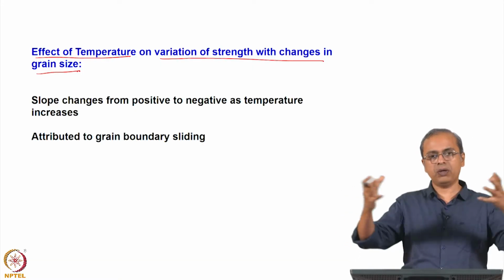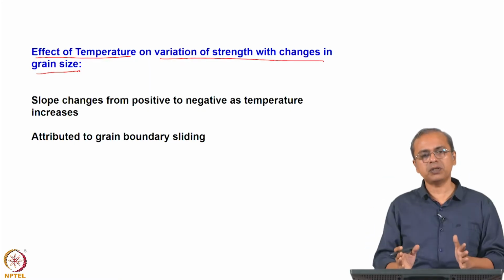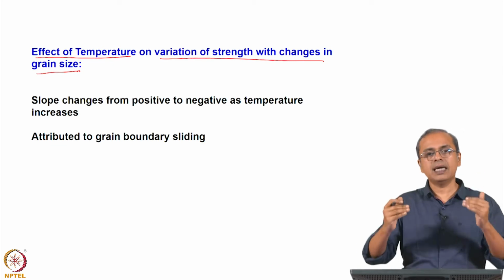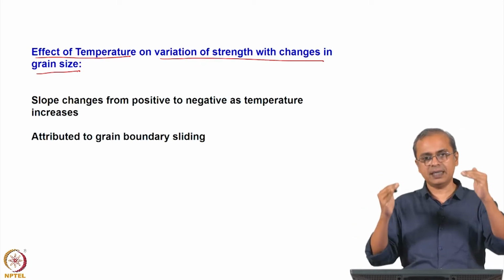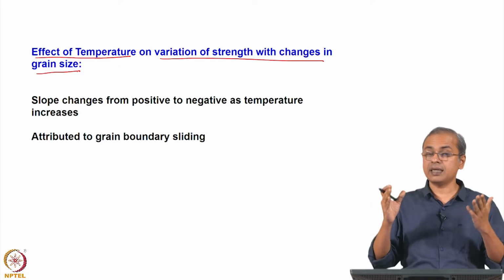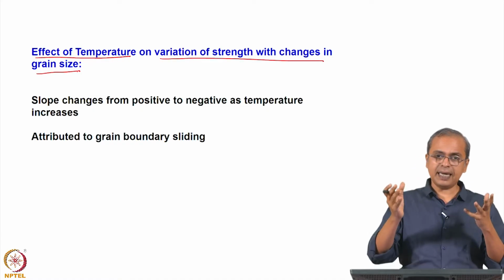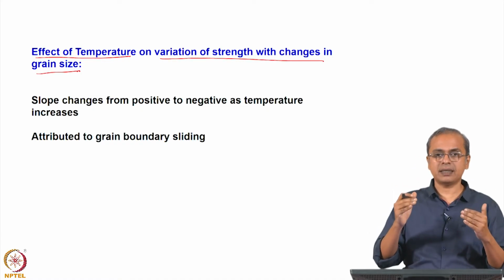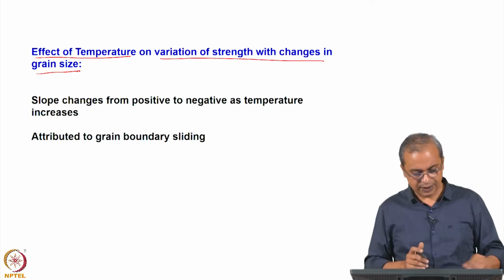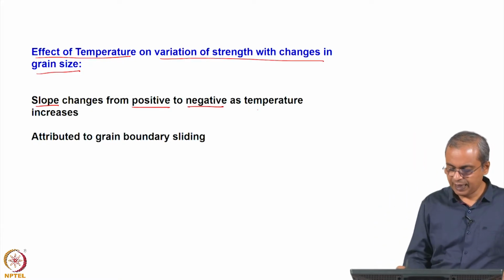So, effectively it is the Hall Petch relationship at one temperature. Then you look at the Hall Petch relationship for the same set of samples at a higher temperature, and you keep on raising the temperature. If you cross some temperature, you see that the Hall Petch relationship inverts. So, at much higher temperatures you find that the slope changes from positive to negative as the temperature rises.